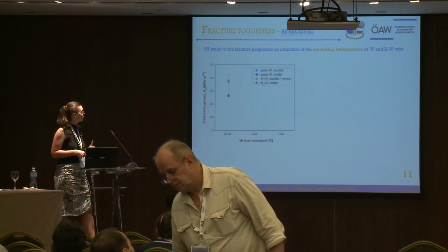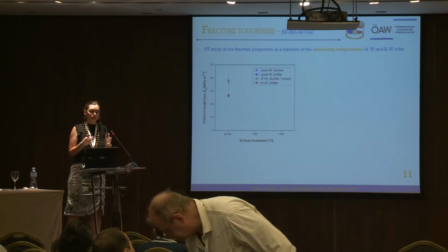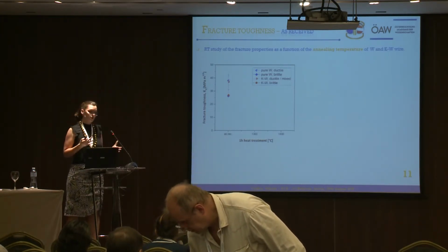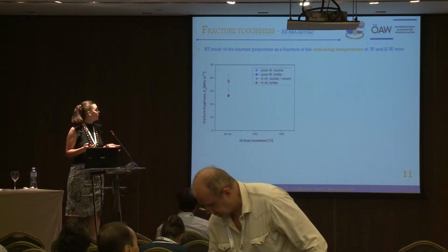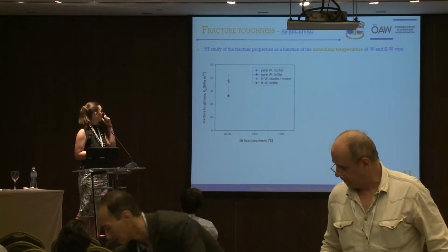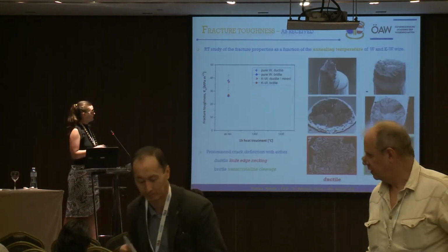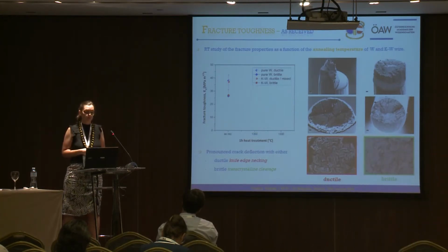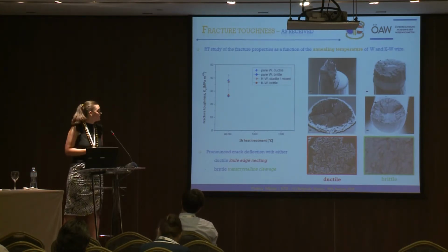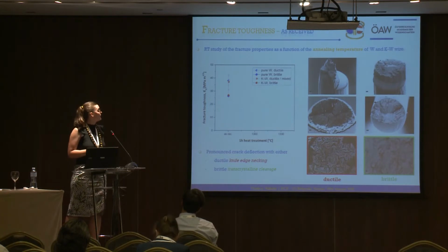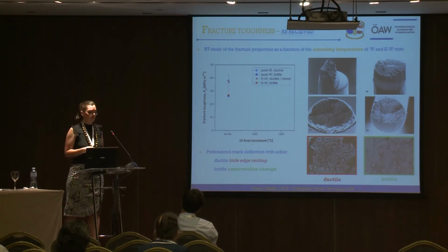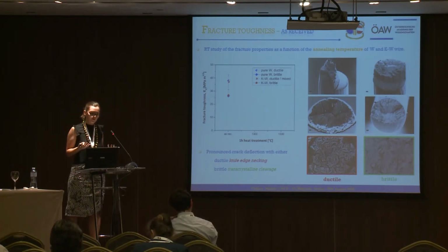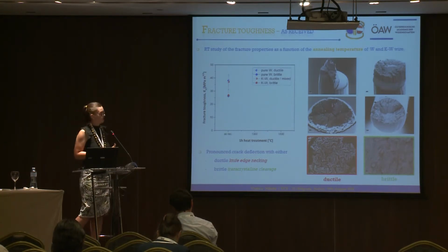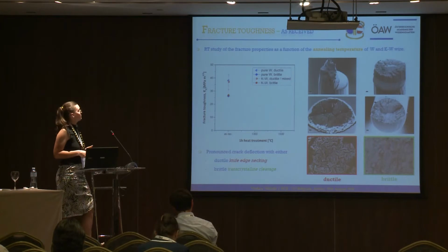Here, if we look into the value of fracture toughness, we see quite a large scatter of data, in the sense that the obtained results are in the range from about 25 to about 40 megapascals per square root of meter, which corresponds to occurrence of both the brittle and the ductile sample behavior. So essentially, some samples failed brittle, some samples failed ductile. And this is a strong indication that DBTT is happening at this range. So we can say it's about room temperature, which was our testing temperature. And that's the first important aspect that we can see.